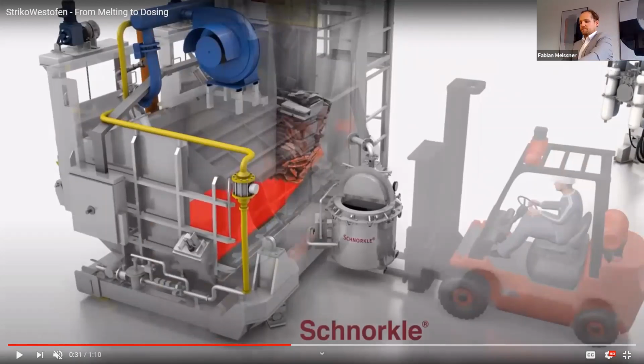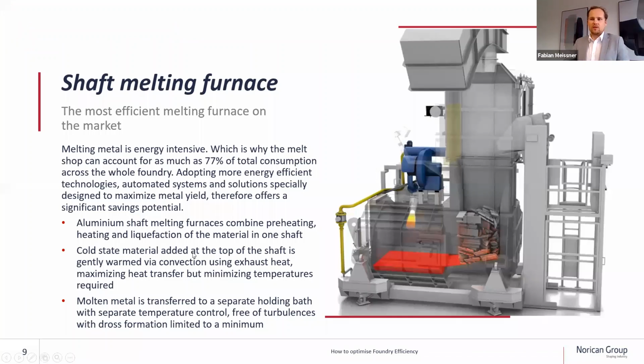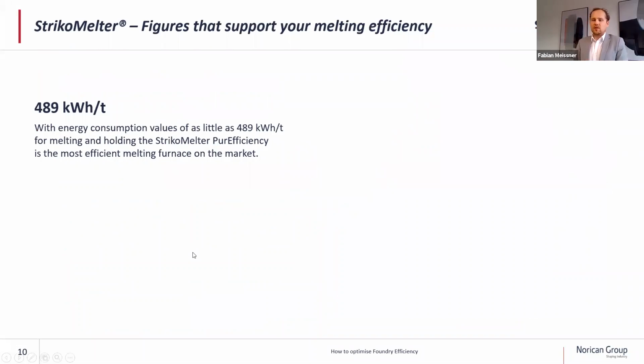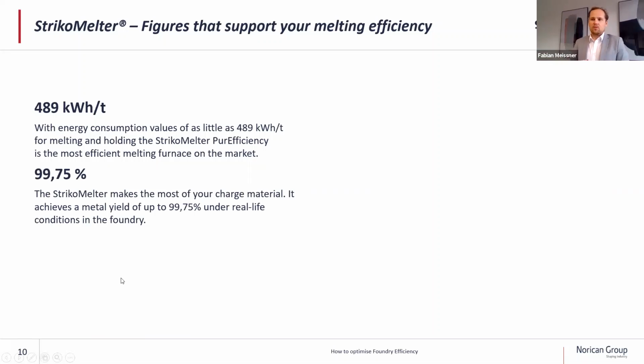So what can we achieve with this technology? We can achieve, as mentioned, an extremely low energy consumption. We have measured values in the field of as low as 489 kilowatt hours per ton of molten aluminum. It is the most efficient melting furnace on the market. We can achieve, or we have measured in the field, a metal yield of up to 99.75% under real life conditions in the foundry.